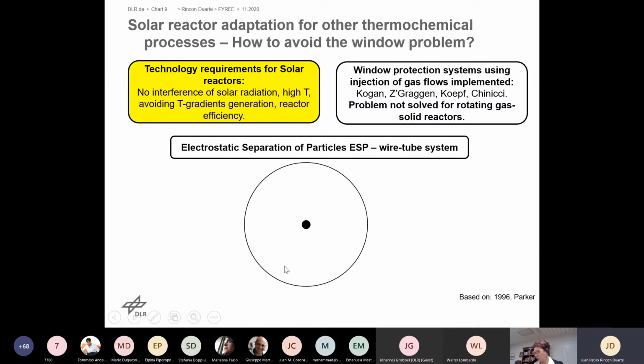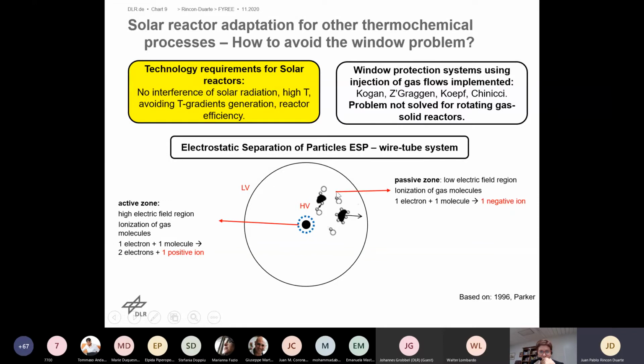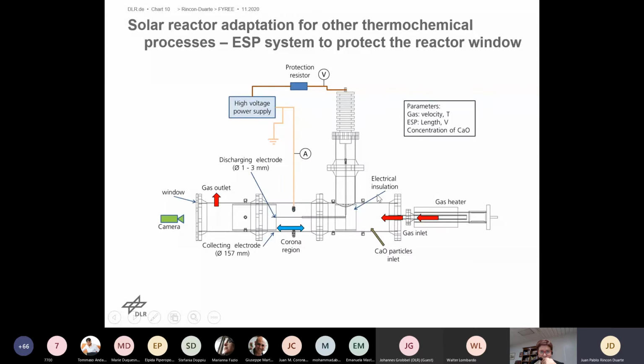In order to describe how it works, I have this diagram. You can imagine this black point as a wire, which is placed in the middle of this circle, which represents a tube. If we apply high voltage to the wire, and the tube is connected to the ground, we can create an electric field between the two elements. This electric field is characterized by two regions. In the region close to the electrode, the energy is very high, so we can remove electrons from the gas molecules. But once the electrons pass to the low energy region, they will attach to the gas molecules, and then these gas molecules will collide with the solid particles, transferring their charges, and the charged particles will move to this grounded surface. So the idea is to investigate this system at high temperature.